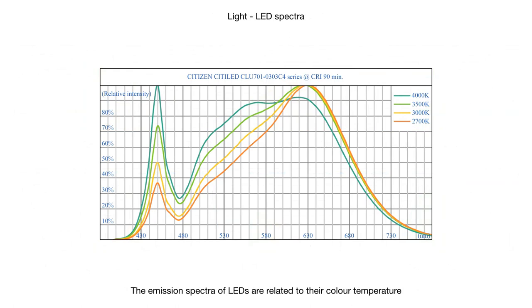Let's look in more detail at the spectrum of a high-quality white lighting LED. There is always a spike in the blue region of the spectrum. The blue spike is reduced as much as possible to achieve lower color temperatures, but with current LED phosphor chemistry, it doesn't disappear entirely. Eliminating the spectrum valley in the 480 nm region is the big challenge in LED research.